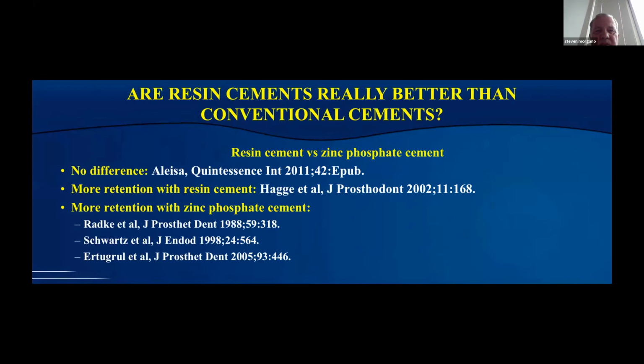So are resin cements really better than conventional cements? So these are some studies on the retentive strength of a resin cement versus zinc phosphate cement. The first study saw no difference. Second study, the resin cement was more retentive, but the last three studies, zinc phosphate was more retentive. And one of the things that we have to remember is the setting characteristics of these resin cements. All dental resins are incompatible with eugenol. Eugenol poisons the setting reaction, and they never really set.